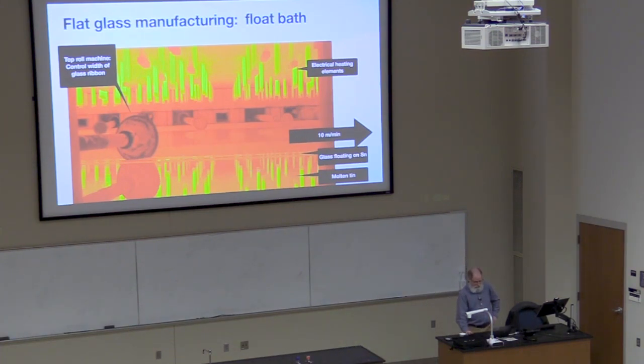You can see down here, this bit down here is molten tin, and you can see it's very flat. So if you want to make something flat, pour it on a flat surface. This is the glass right here, and you can see a little change in color, a little change in reflection there. This ribbon's moving about 10 meters a minute, as I said. These are heating elements up here, because you've got to keep the temperature uniform and controlled. And then you can see the reflection of these heating elements in the tin. These are the machines I referred to a minute ago. They're called top roll machines. You can see it's got a little knurled wheel. And so those grab onto the glass, they pull it out, and keep it going in the right direction. So we'll come back to that a little bit.